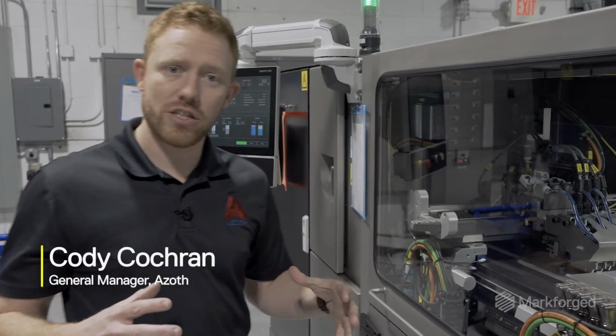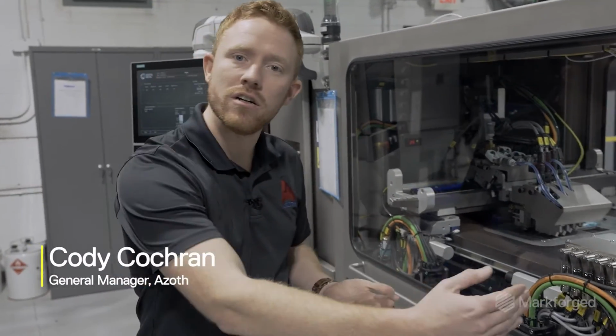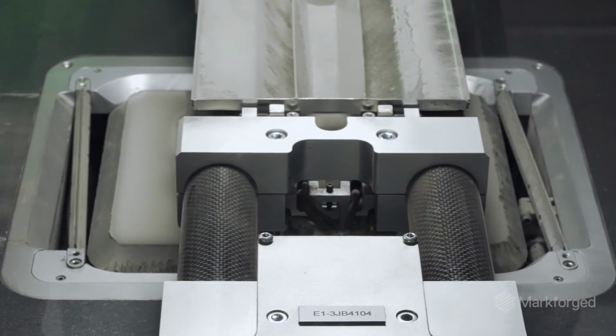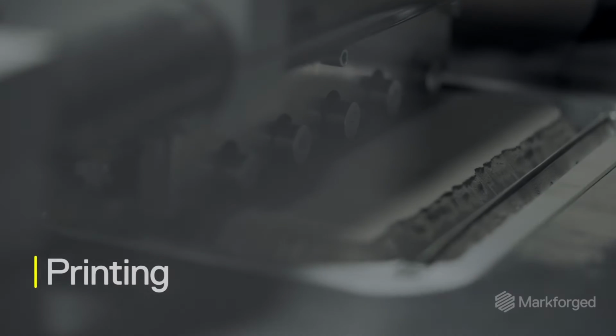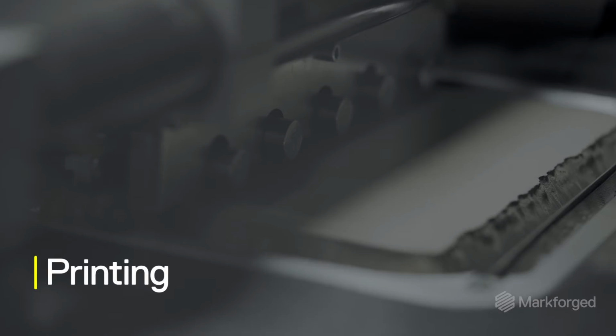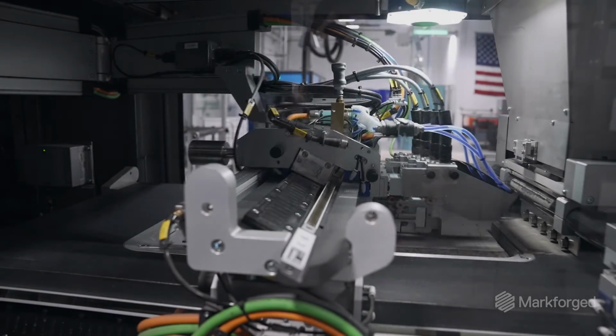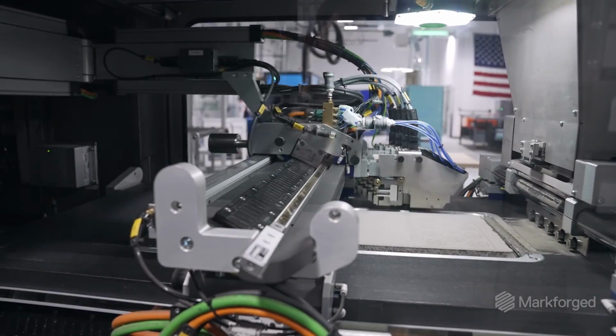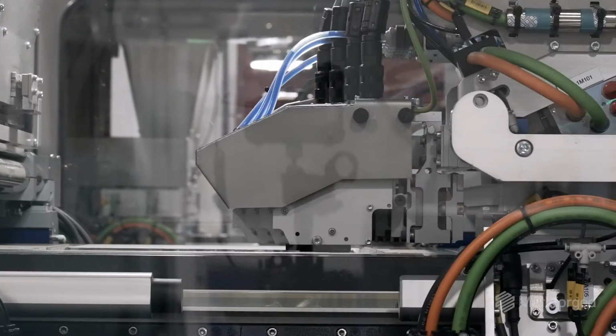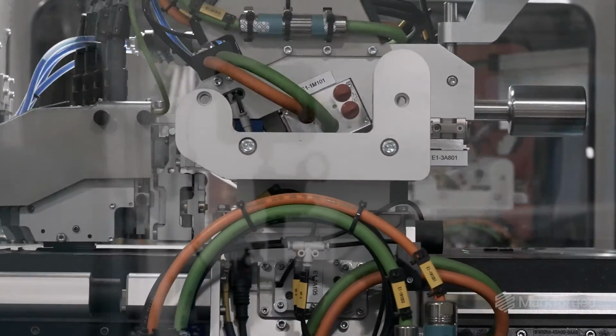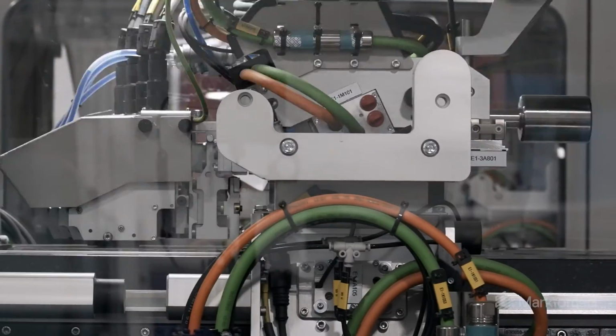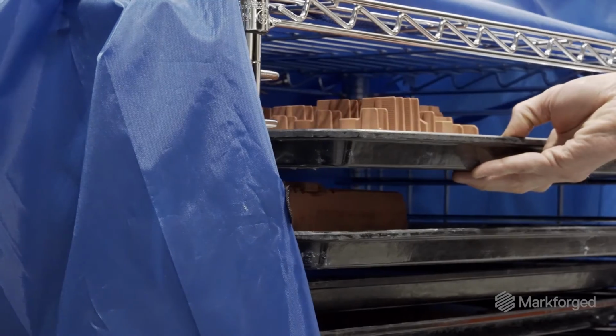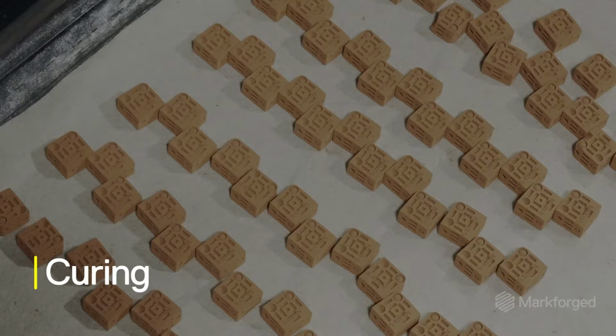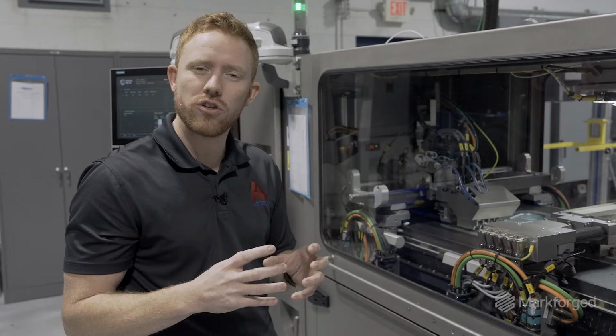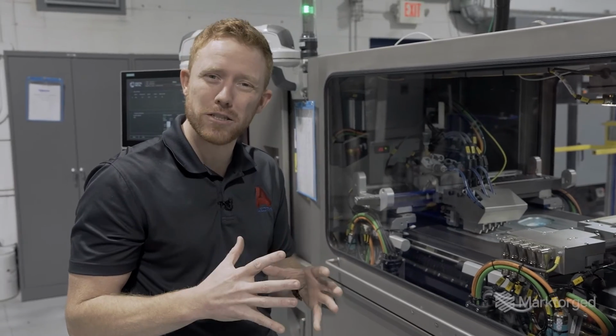The way it works is you're going to lay a layer of powder, in this case, roughly 42 microns thick. And then after you lay that layer of powder, you selectively deposit binder in the cross section of your parts. And we'll continue that over and over until we build up the entire Z height of the components. Once we've printed, we'll go through a curing step, which heat activates the binder. Basically, it locks all the metal powder into place.